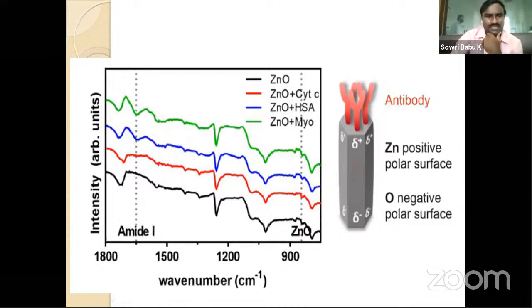So if you see here, this black one is the FTIR of zinc oxide, the red one is cytochrome C, and the third one is serum albumin. For HSA and myoglobin, a new peak evolved at around 1650. But we don't have such a peak in cytochrome C. Which confirms